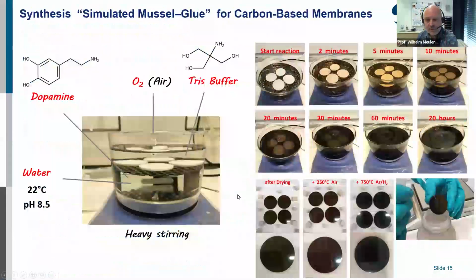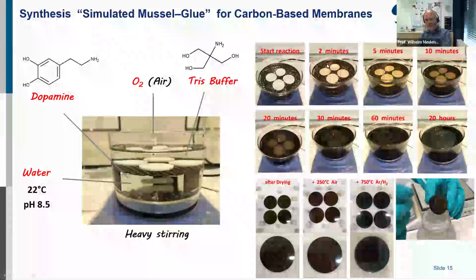So what we did then is we made, in principle, a water-based solution. We took dopamine from the mussels. So from this bio-inspiration, we mixed it into our water. We also have a buffer inside, and then we stirred it heavily and put our planar supports into this liquid. And then we can see that the reaction starts immediately after a few minutes. After 20 minutes, you have a gray layer. And after 60 minutes, you have a big black graphene dopamine layer on the surface.